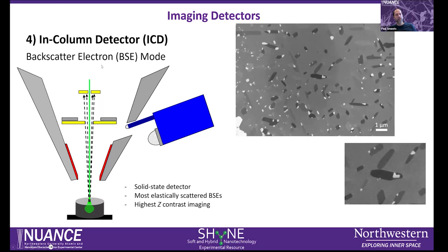The fourth detector is the in-column detector. That's a detector located at the highest location up in the pole piece, which really collects the most elastically scattered backscattered electrons and gives you the highest Z contrast image with the highest signal to noise.